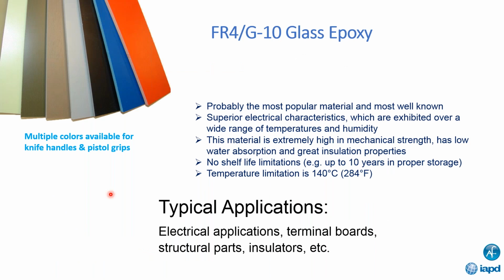So the first material, FR4/G10 glass epoxy. This is probably the first laminate material that most people hear about. It is by far our most popular material and most well-known. It's got great electrical characteristics. It's extremely high in mechanical strength. Temperature range goes up to 140 degrees C.